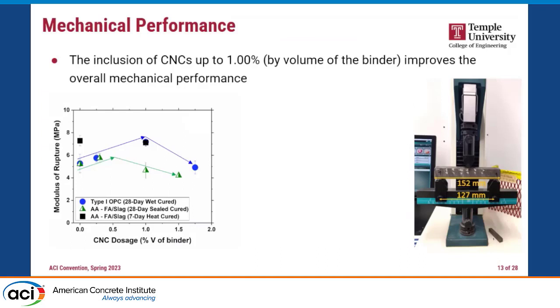Regarding the mechanical performance, by inclusion of the CNC, this is the modulus of rupture versus the CNC dosage. Up to a certain percentage, again, we see an increase in the flexural strength, or the MOR, of this system by use of the CNC. By using heat curing for the alkali activated, we see much more improvement, the black dots you are noticing here. The other point to notice is that the reduction at the higher percentage is partly because we are using a higher water binder system, which reduces the mechanical performance.